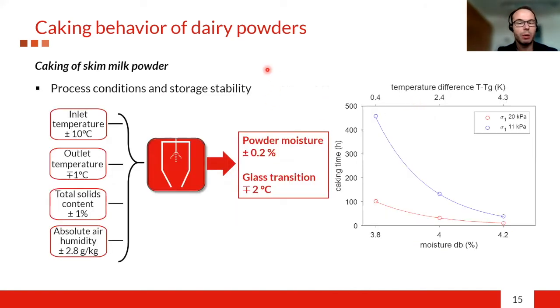Here I want to show you how it's now possible to change the moisture content in the spray drying process. On the left-hand side, the drying air conditions or drying parameters are listed, for which the magnitude of the influence is known for the powder moisture content: the inlet temperature, the outlet temperature, the total solid content, and the absolute air humidity. The variations shown lead to an increase or decrease in the powder moisture content of 0.2% and a change in the glass transition temperature of 2 degrees Celsius. So, for example, a decrease in the outlet temperature by 1 degree Celsius will increase the powder moisture by 0.2% and will decrease the glass transition by 2 degrees Celsius.